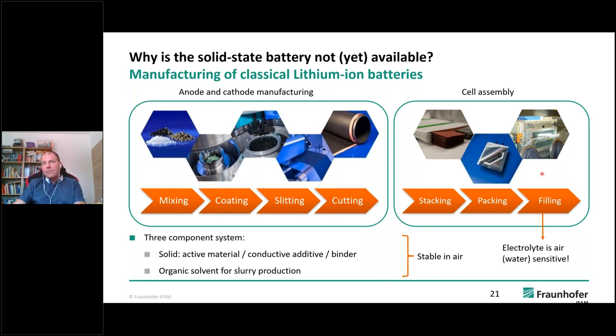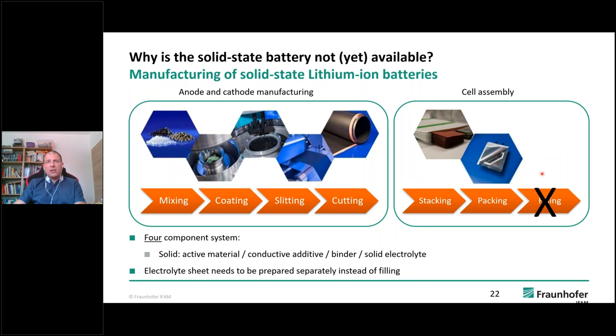because we know that it's reacting with the electrolyte. When we're switching to solid state batteries and try to keep at least most of the steps the same, the filling step can be removed, because the solid electrolyte has to be already inside of the cell while producing anode and cathode. But we are also adding a component, so we have now four components rather than just three components beforehand. And we need to have three layers, then we have to have three rolls: electrolyte, cathode, and anode.